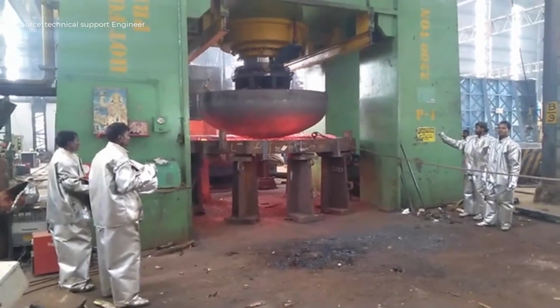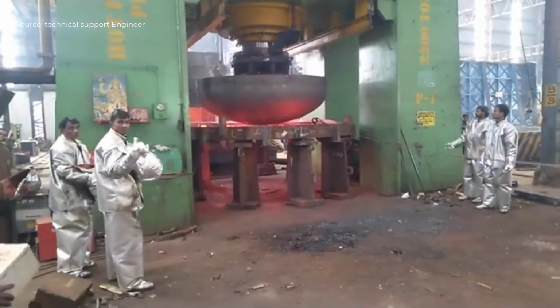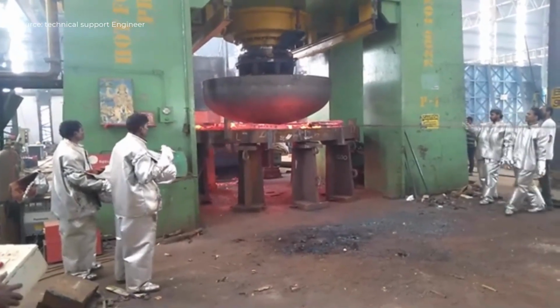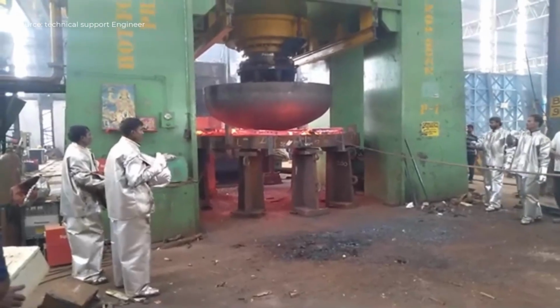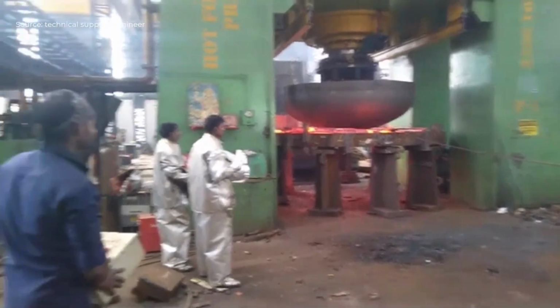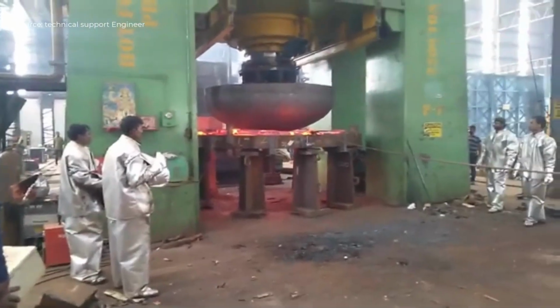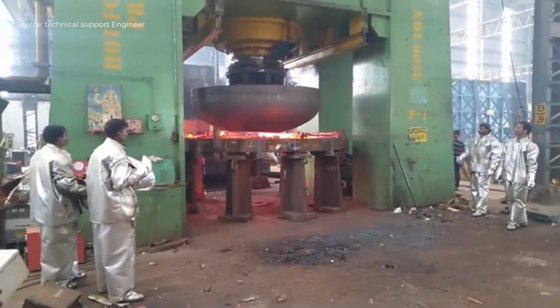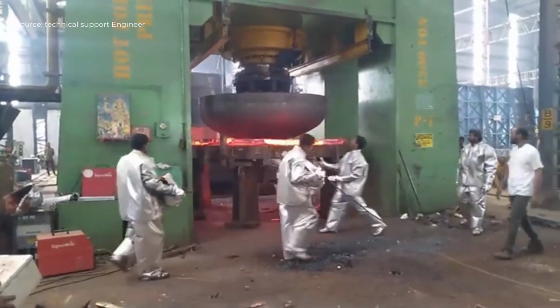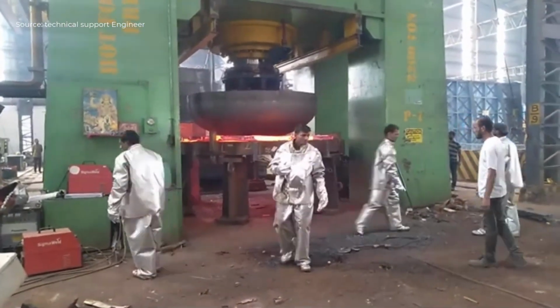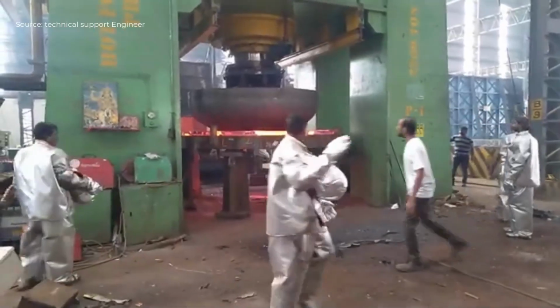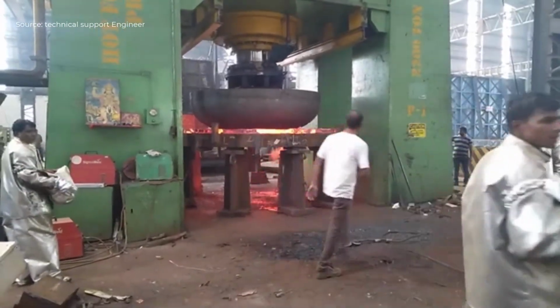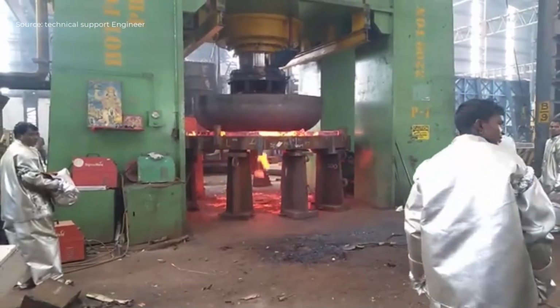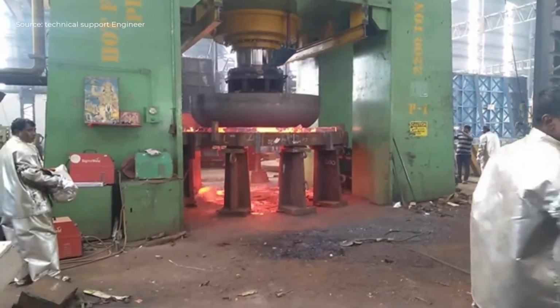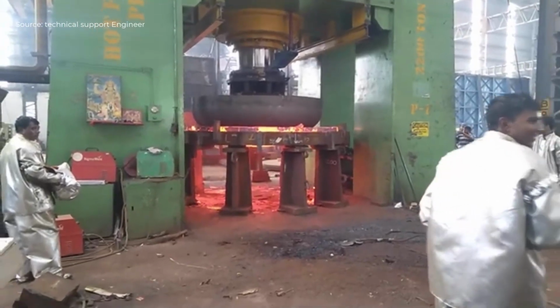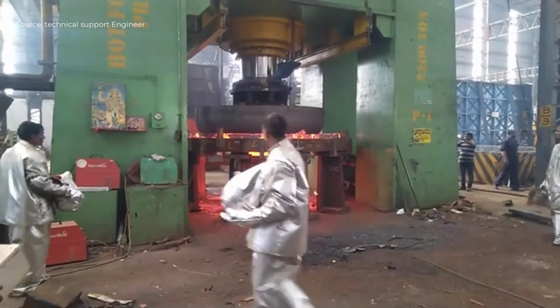The hot forming process of dished ends begins by placing a metal plate into a furnace, where it is heated uniformly to a high temperature above its recrystallization point. Once the required heat is achieved, the softened plate is transferred to a hydraulic press. There, it undergoes a pressing cycle where a die gradually forces the plate into a concave shape, forming the initial curvature.